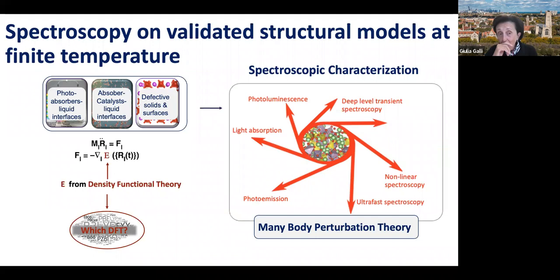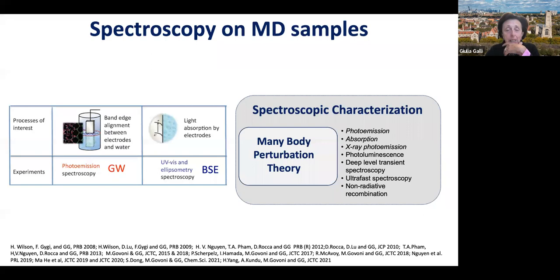spectroscopy on complex systems. So we have been worried about accuracy, but also about efficiency, because the systems that we look at contain many atoms, and many from the point of view of first principle calculation means hundreds of atoms. I'm not going to tell you the specifics, but let me tell you just the general idea of what we have done. So we do first principle molecular dynamics, and then we do spectroscopy on MD samples. For example, suppose that you want to know band alignment, and I will get to that in a minute, between electrodes and water. What you need to know are positions of energy levels that you would get experimentally by doing a photoemission experiment.